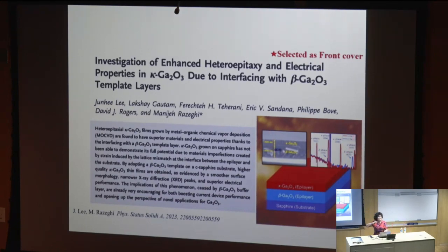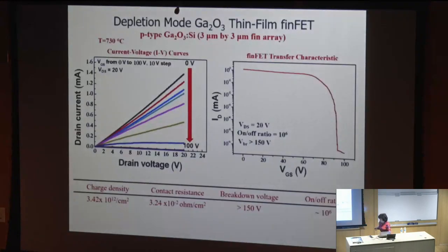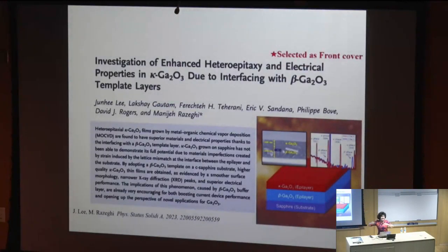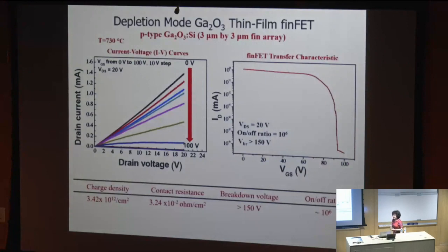And now, the nitrogen phase of the aluminum nitride and gallium aluminum nitride are polar. So if you grow this material on the gallium oxide, on the nitrogen phase of aluminum nitride, gallium aluminum nitride, you can have a very high two-dimensional electron gas. On the other hand, the p-type is the real problem. So we demonstrated again, by using the silicon as an amphoteric dopant, the p-type for the first time. But I explained to you, when you have a new material, nothing can prove better than the device, the device can speak. No theory, no characterization, whatever they have, but the device can speak.